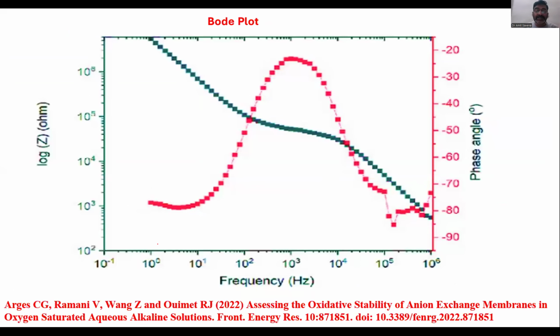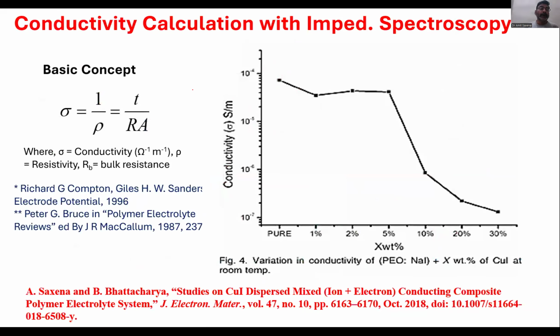And this is the Bode plot diagram, which has been taken from this reference to make it more understandable. The frequency and log of Z will give this sort of graph, and the frequency with the phase angle will give you this information, and this is the highest peak by which we can find more insight on the phase. This is the formula which I mentioned earlier, the conductivity-based system, and I'm coming down to three theoretical models which can be used to understand how this conductivity pattern goes.